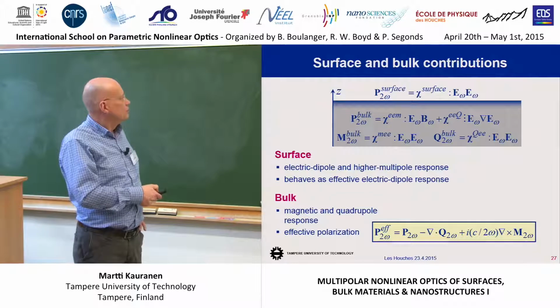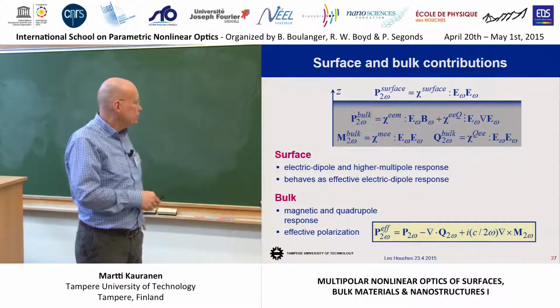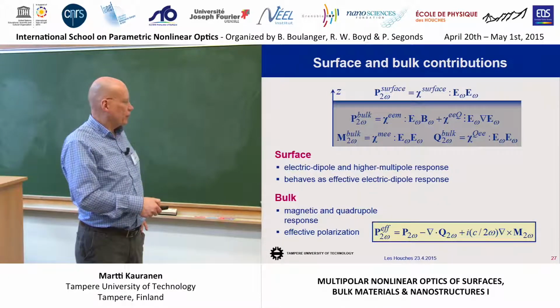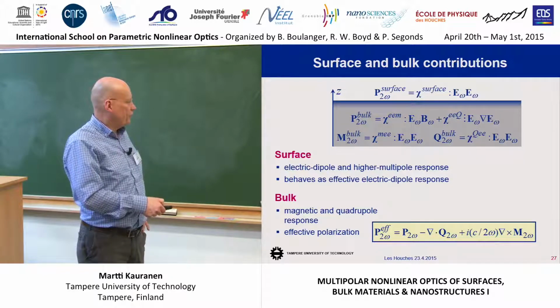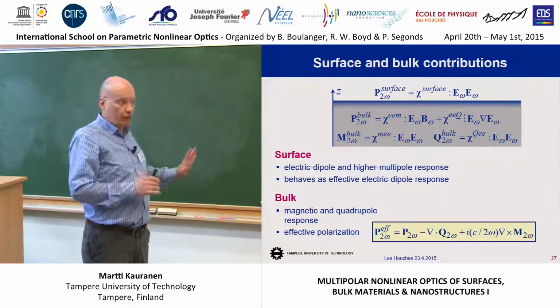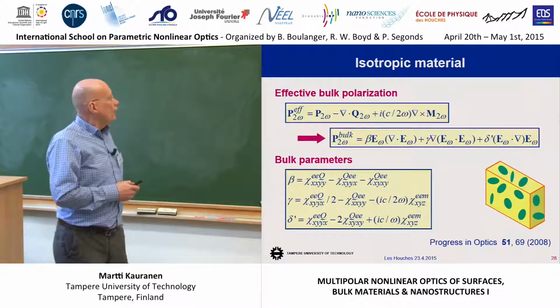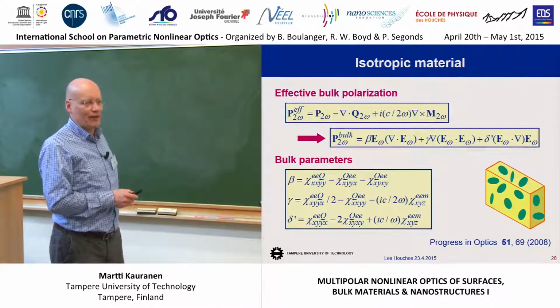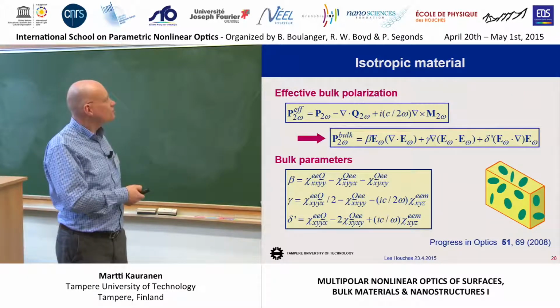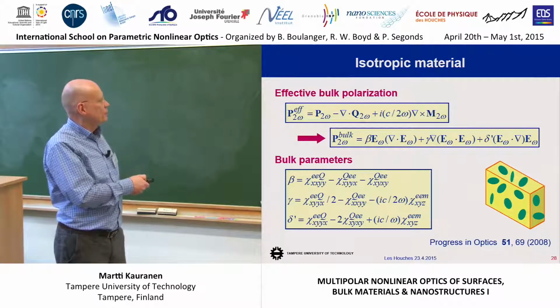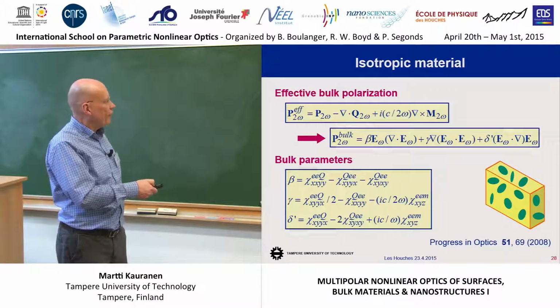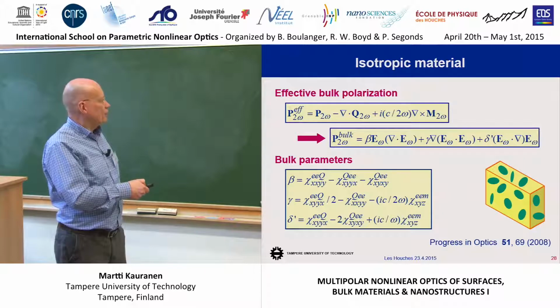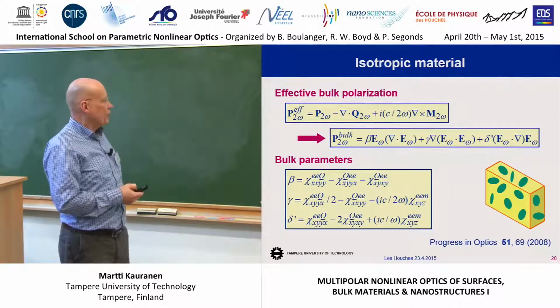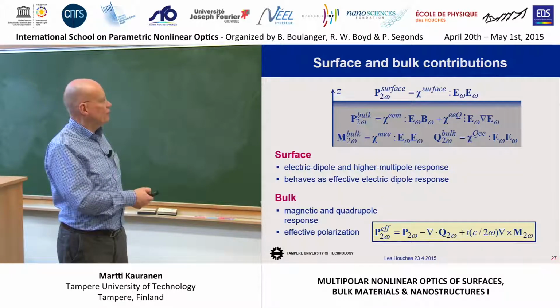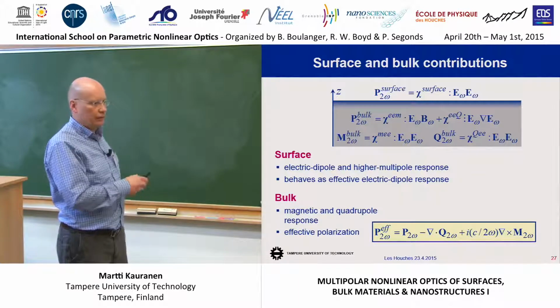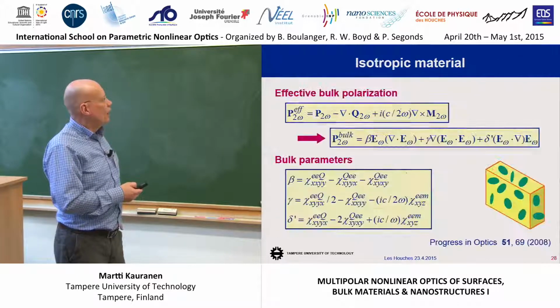So in the bulk, to take all these higher multipole responses into account, we can calculate the effective polarization, which we already discussed before. So combine the dipole, quadrupole, and magnetic sources into one effective polarization. Okay? And then I'm using the same slide that I had last time. But the point is that when you calculate this effective polarization, you come up with these 3 parameters that define the bulk response. And when you do this calculation, you already take into account all these details of the symmetry operations. For example, the fact that this MEE tensor vanishes because of the permutation symmetry for second-harmonic generation. Okay? And so on.